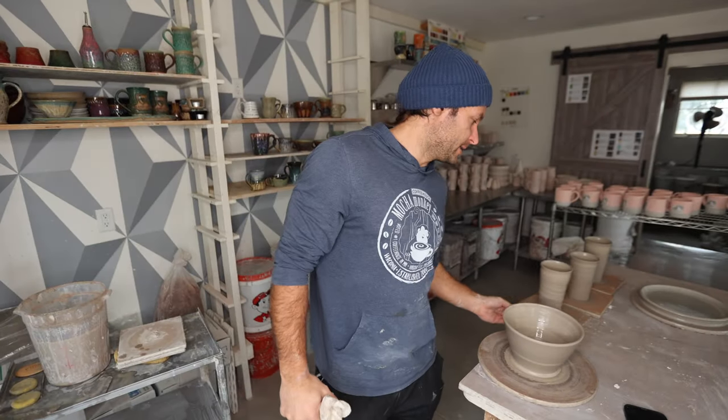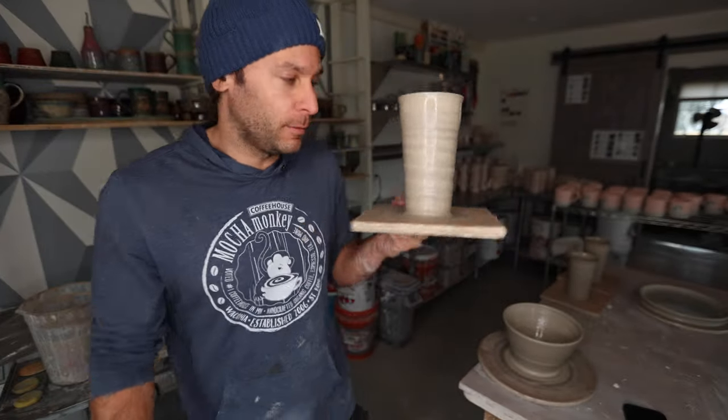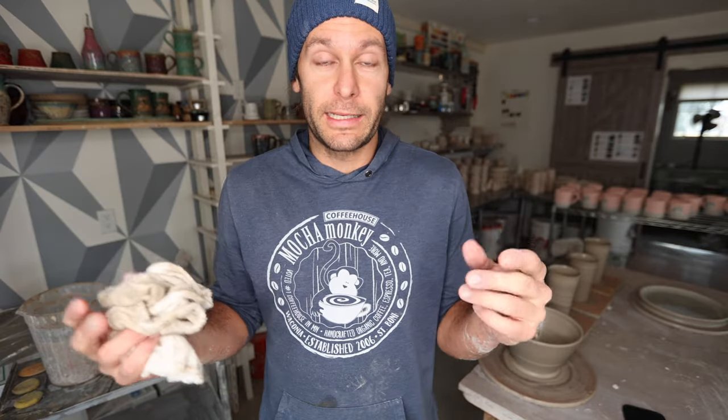That's it for this video — got just a couple of those thrown. Hopefully that helps. Trial and error — the first batch I threw was too small, and the next batch was good except one was a little too big. You've got to test your own clay. Most clays are about 15% shrinkage but some are more like 10 or 11, and it can depend on what cone you fire to. Just like with all things pottery, trial and error testing is super important.